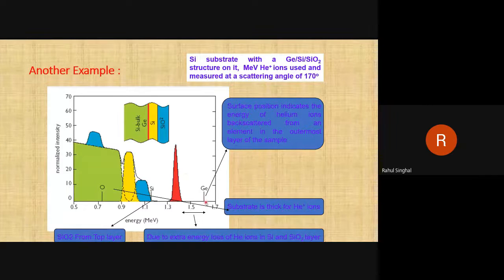One more thing I would like to tell you: I have marked germanium here. This is the position of the germanium, meaning this peak should have come here if germanium was at the top. Suppose instead of SiO2 you have germanium on the top, then the actual position of germanium is here. But now germanium is not on the top. It is going into some depth of your sample, and that's why the peak is also shifted. Suppose we have another layer of germanium here, then one more germanium peak will come something like here. All these things I have written here.